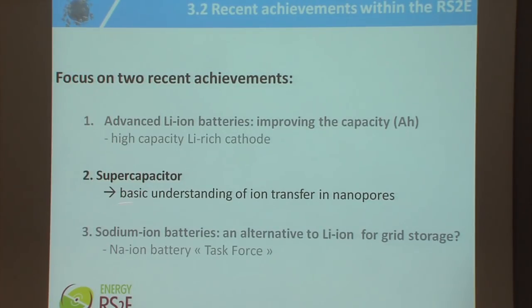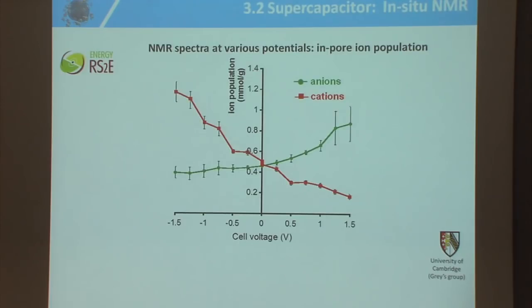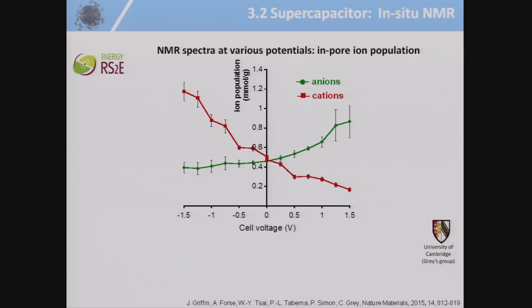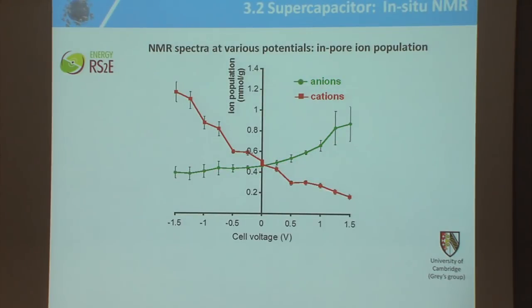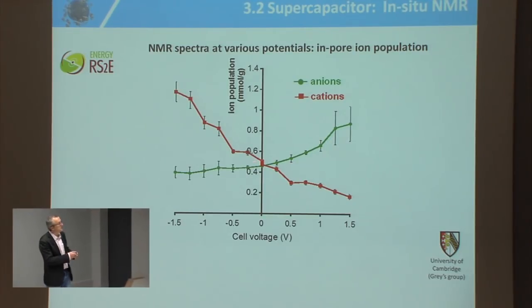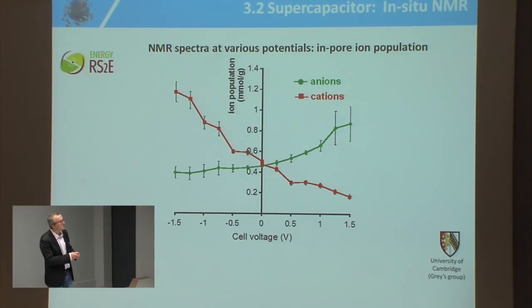On supercaps, what we did was to try to understand the ion transfer in nanopores, and we did some in situ NMR spectra together with Clare Grey at Cambridge. And you can see here, we took a cell, we did some polarization at constant voltage, and we have tracked the signal of anions and cations by following the fluorine and the phosphorus signal. And you have here, during positive polarization, the number of anions and the number of cations. You polarize positively the carbon, you can see that anions enter, cations are leaving, normal. But when you go to the negative polarity, when you polarize negatively the carbon, cations are entering, normal, but anions here, constant. They don't leave.